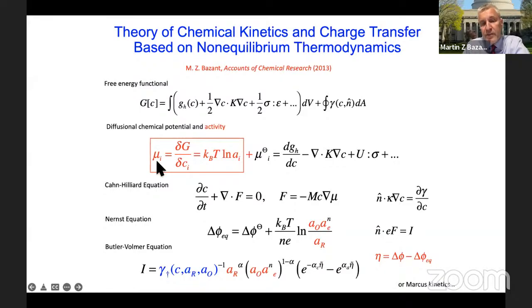So I write that the chemical potential is a reference value, mu theta here, plus kT times log of activity. So now the activity, which is an important concept in chemical reaction kinetics and thermodynamics, is connected to these variational derivatives of the free energy. And if you carry out that variation in this particular example I gave you, you get the terms shown here, where, for example, the gradient term turns into a Laplacian term. And anyway, once you have chemical potentials, you can define both transport and reaction kinetics in a consistent way.